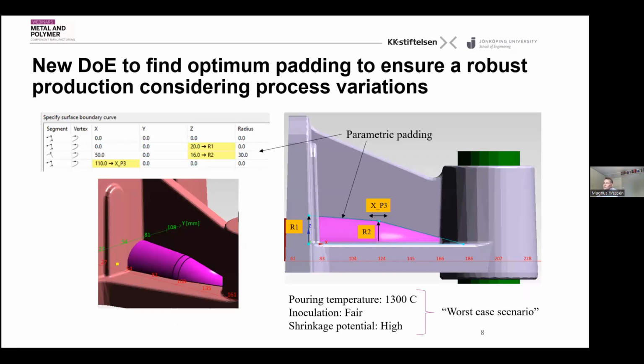Again, this could be from a designer's perspective. They would like to do this by themselves before sending the part to the foundry. They could optimize the geometry. In this part, this padding material was designed as a surface which I was rotating around this axis. Then I can define this extra volume, or this padding volume, by radius 1, this height here, the radius 2, and the position of this point. So I can shift this point in this direction. In this way, you set this up with the worst case scenario. So now I will create lots of new designs, but I will only run them with the worst pouring temperature, the worst inoculation, and the worst shrinkage potential.